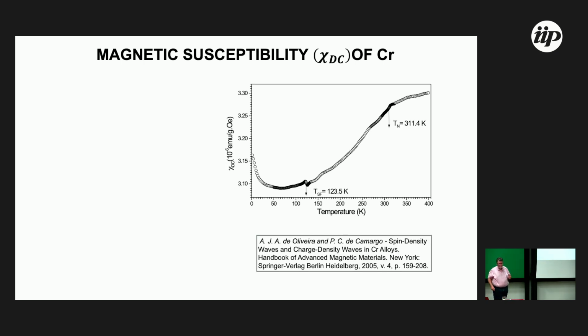Okay, chromium is an antiferromagnetic system. What about the magnetization or magnetic susceptibility behavior? This is an important point. This measurement performed in my laboratory on chromium observed that the susceptibility decreases with the increase in low temperature. It's not expected for antiferromagnetic behavior, because for antiferromagnetic behavior an increase with temperature is expected. This is a point, a Neel point. No direct explanation for this behavior.